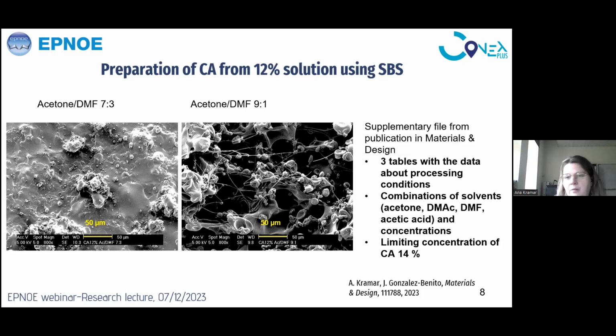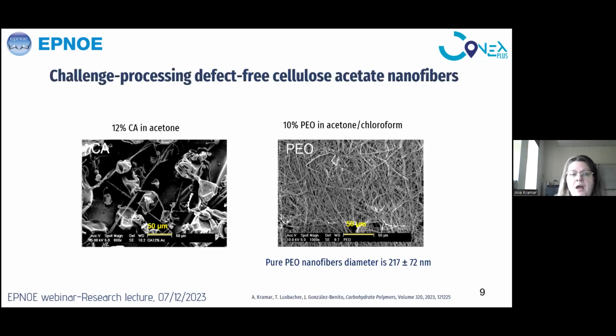And we gathered this and published it at the beginning of this year in the journal Materials and Design. You can see we have supplementary material, three tables with the data about all the processing conditions that we used. We used a lot of combinations of different solvents, which included acetone, as mentioned, DMF, acetic acid, dimethylformamide, and various concentrations. And we found that in our case, in our device, the limiting concentration of cellulose acetate is 14%, but we opted to continue with 12% solution. So we wanted to address the challenge of how to process defect-free cellulose acetate nanofibers using this novel solution blow spinning.